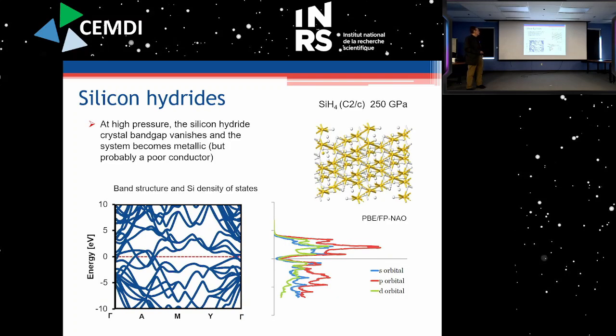Up to a point where at high pressure, and this is the crystal structure that we get, at very high pressure, the band gap actually closes or vanishes. So where the 0 here is the Fermi level, and the system becomes metallic. All right, so we have to reach a pressure of 250 gigapascal, and you see that now we're closing the band gap here of the orbitals. So this motivates investigations of materials under high pressure conditions to also try to stabilize material phases that may not be observable under normal conditions. All right.